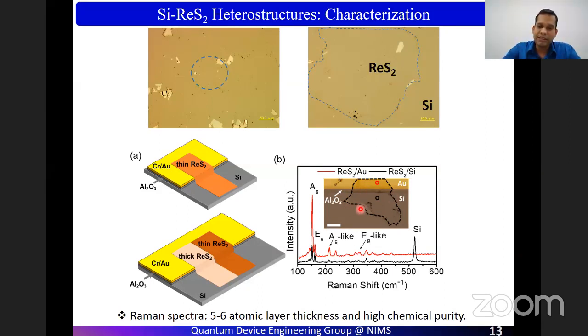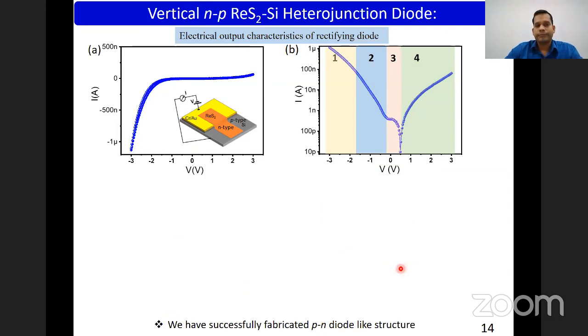In the initial characterization, Raman shows the out-of-plane mode and in-plane mode of vibration, which further confirms the high chemical purity of this material, and it confirms ReS2. And so the typical characteristics, which we first do, are the IV characteristics across this diode, and it shows a highly rectifying feature, which you see here.